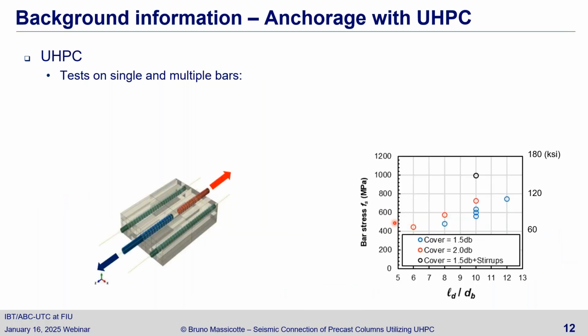If you pull on a bar, let's say you pull on that bar here, and you look at what kind of stress you can develop, you can see that for 8 bar diameters of anchorage, you can go to stresses around 60 KSI. So you can easily yield the bar with 8 bar diameters and break the bar with a 10 bar diameter embedment length.